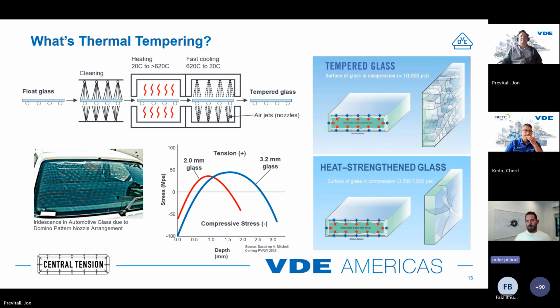So in the bottom right-hand corner, if you've worn polarized glasses or you see these small circles in automotive glass and architecture, if you see sort of ripples or stress patterns, especially with polarized sunglasses, these are the nozzles that are cooling down the glass during this thermal tempering process. So another thing to walk away with is that you're getting differential stress patterns within the glass because of where the nozzles are that cool down the glass.